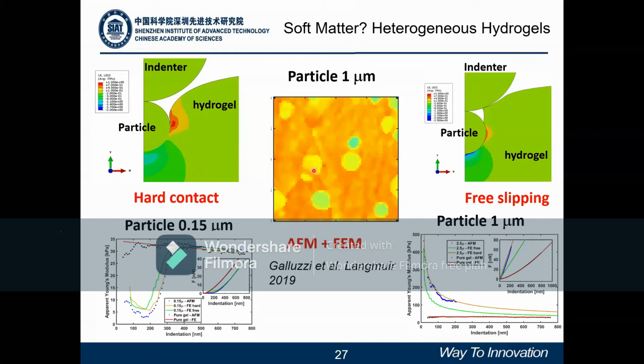Here we prepare a simple system of two phases, a sphere embedded in a soft hydrogel, and after the indentation on them, we perform finite element simulation with different geometry, also trying to understand how the interface between this particle and the gel is. So the model of free slipping, when the particle is not attached to the hydrogel and it can rotate inside the matrix, or when there is a hard contact and then all the points on the particle cannot move. In this case, we measured that the hard contact is the most suitable for describing this system.